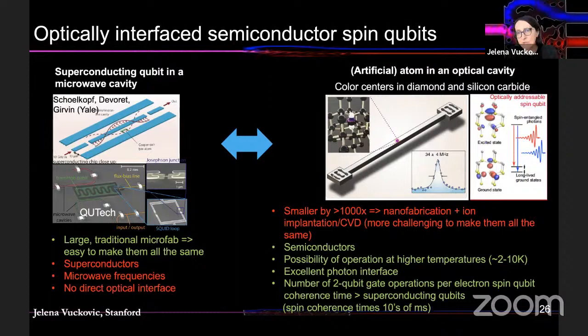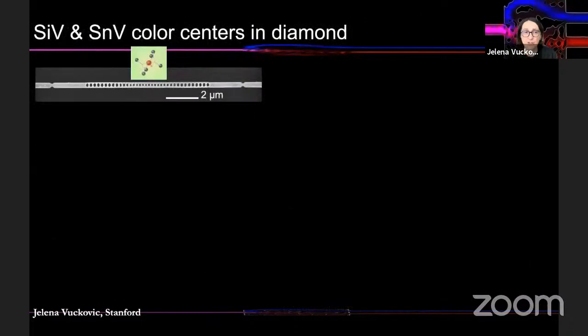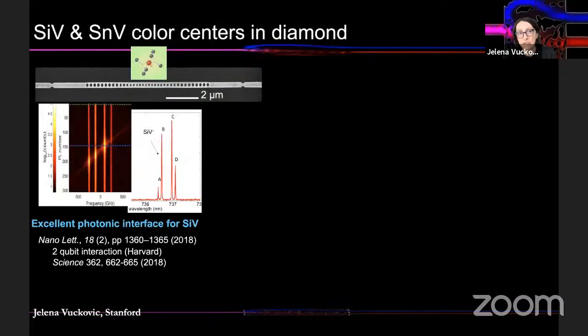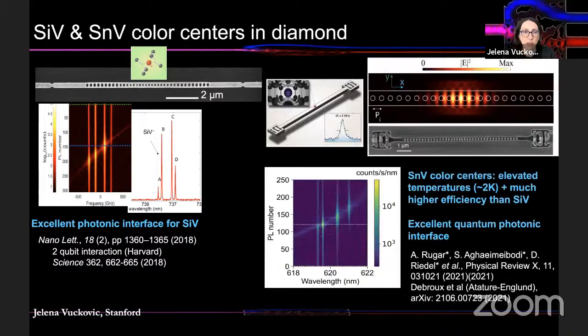You really literally have to insert these impurities at the desired positions with minimal damage to the lattice, as opposed to superconducting circuits where you define everything lithographically. So of course, the technological challenges are much larger, and that leads to a lot of inhomogeneities in the system that we've been trying to address over the years. So for us, the choice of these spin qubits, and we work really on optically controllable spin qubits, are spin qubits in impurities in diamond, such as silicon vacancy and tin vacancy color centers in diamond. And they're essentially 2 missing carbon atoms and 1 silicon or tin atom embedded in between.